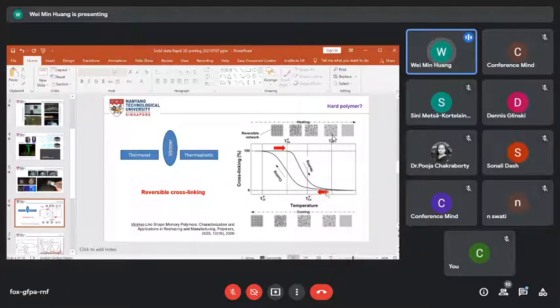Upon gradual cooling, the cross-linking reappears, and up to this point, it's fully reversed back to the original cross-linking state. So we have an internal reversible cross-linking system inside of vitrimer, and when the material melts, it is still cross-linked, because for the cross-linking to disappear, we need to heat up to a much higher temperature, for example 30 degrees above its melting temperature. You may be wondering, is there any such material?